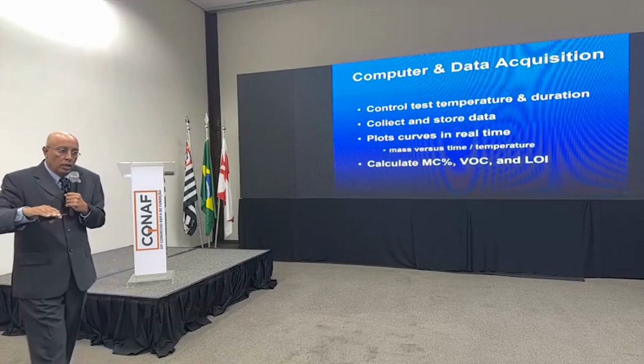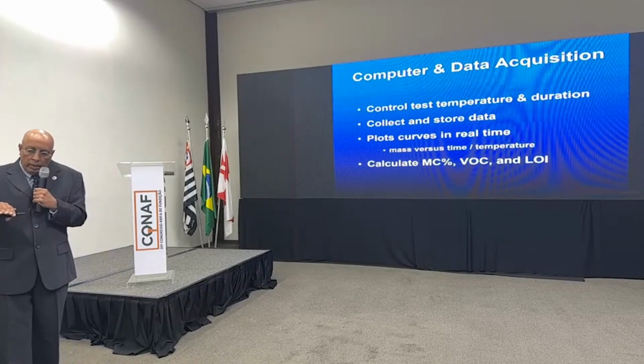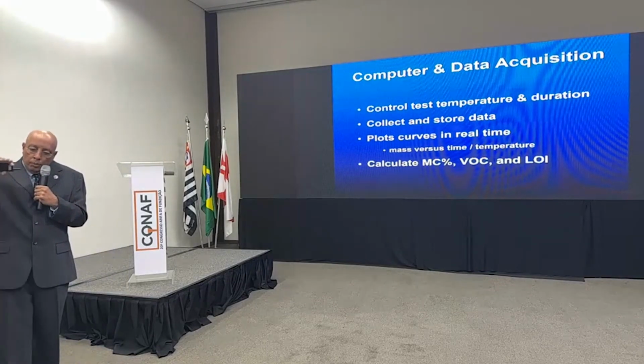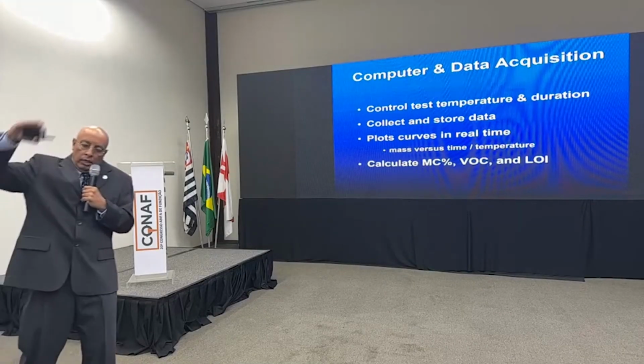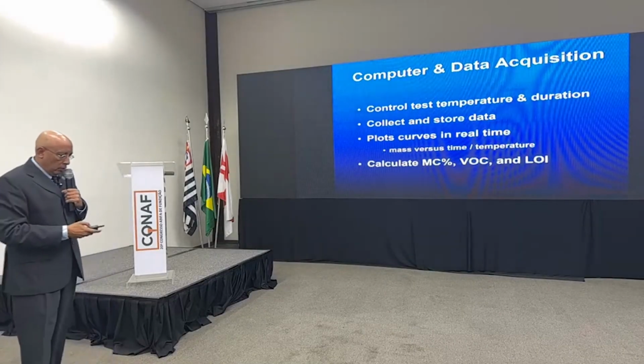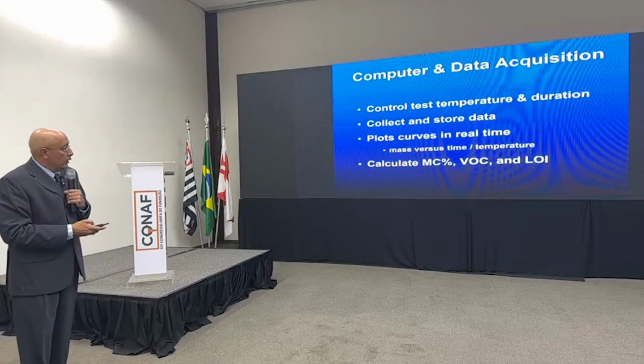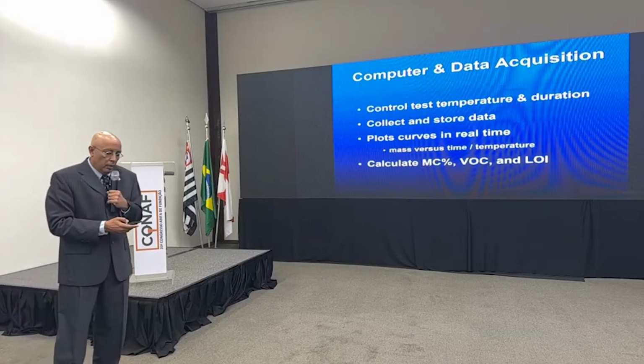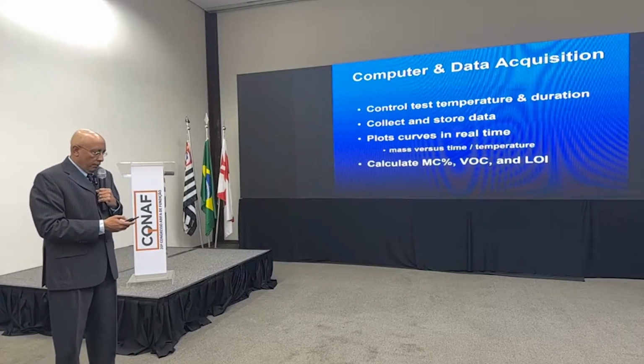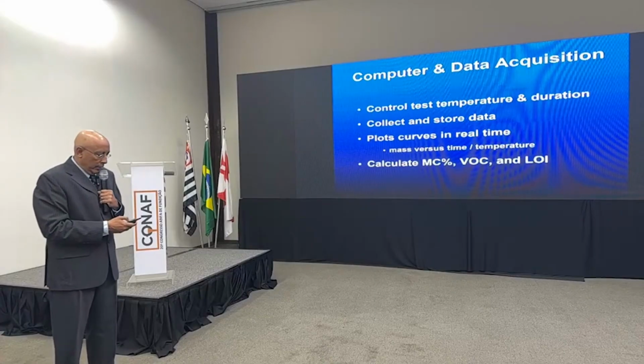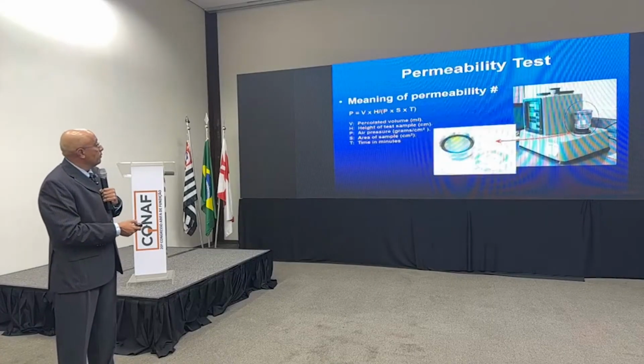So we check moisture. The moisture indicates dry sand. We move and we measure the VOCs, and then we measure the total organics of the sand system. And again, this today can be achieved in 5 minutes as an AFS standard.